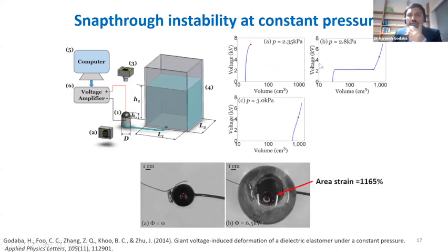So when we do this, what we saw is that when we have an initial pressure very low, no matter how much voltage you apply, the membrane will try to increase, but it will never reach snap through, and it will just break down before it can get any large volume change. So the volume change is very small. And at very large initial pressure, the membrane already undergoes snap through, so there is no more actuation you can get, which will also be very small.